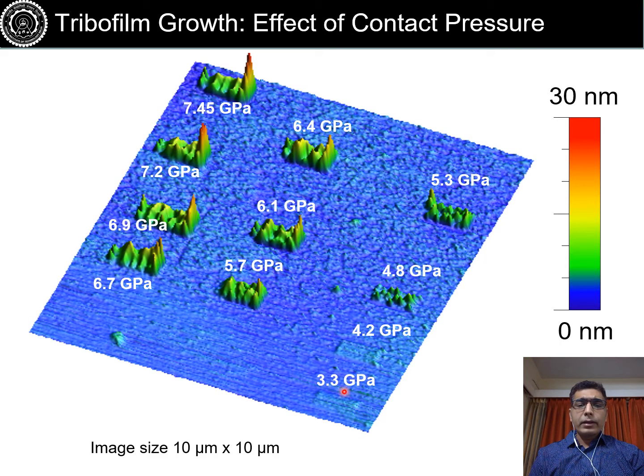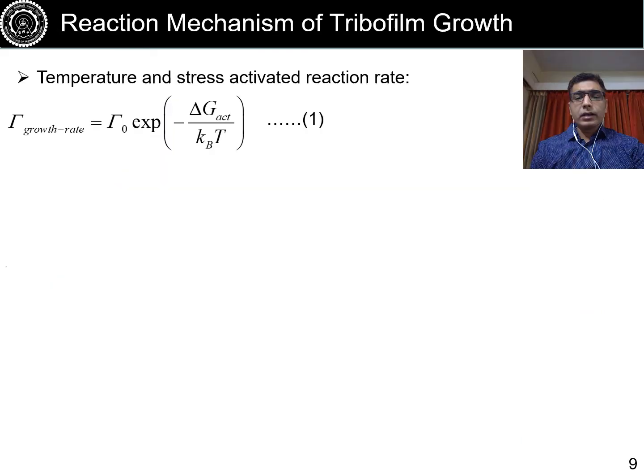And then we did a very systematic study as a function of contact force, which will vary the contact pressure. So in terms of increasing pressure, we saw that film growth for a given sliding time is thicker for higher contact pressure. So as the pressure is increasing, film thickness is also increasing for a fixed sliding time. And of course you start to see wear or deformation of the film when the pressure becomes too large. So in order to understand how this pressure is affecting the reaction, and another parameter is the temperature, we saw that this reaction did not happen at room temperature. So how to take into account these parameters? We try to analyze it in terms of a simple chemical reaction.